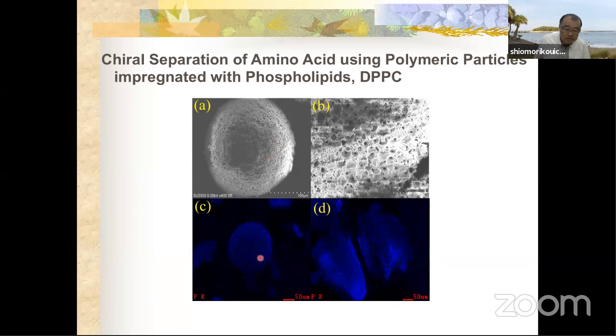So this photograph shows the X-ray emission by EDX from the phosphorus element. DPPC covers the surface and pore like this. Usually DPPC forms a liposome. Liposome is a quite unique basic two-layer molecular particle. So this liposome has shown the chiral selectivity of the L-type amino acid.